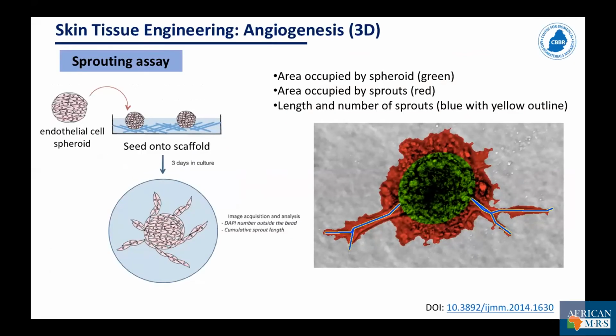Now we can also use a 3D cell culture system to test for the angiogenic potential of scaffolds. We can use, for example, the sprouting assay. So in the sprouting assay, we're going to fabricate endothelial cell spheroids. These spheroids will then be seeded onto scaffolds, and then we're going to monitor the migration of cells from the center of the spheroids towards the nanofibrous mat or your scaffold. And this here is known as the sprout.